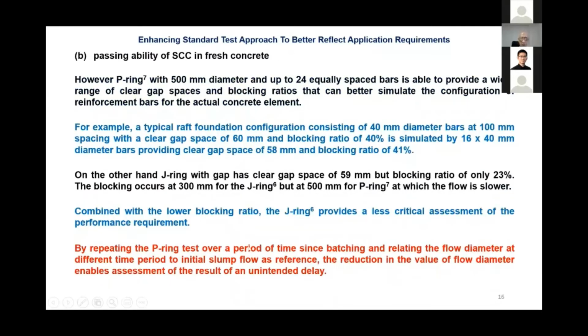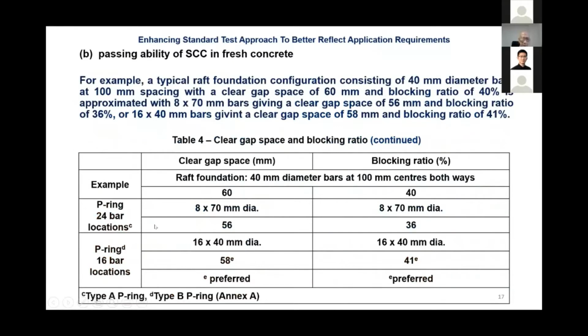So you can see now, I can simulate that with very big diameter bars. To get the 60 and 40, I can use 8 bars of 70 mm. That will give me close to 56 and 36. But if I use 16, 40 mm bars, I get 58 and 41, even better.